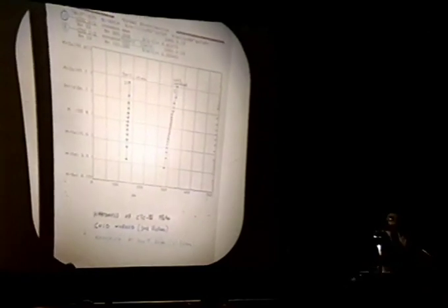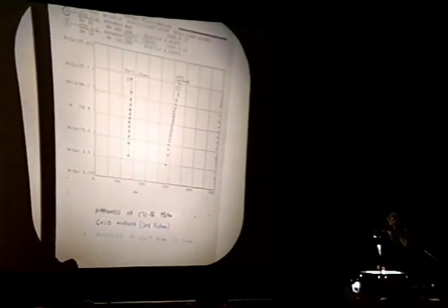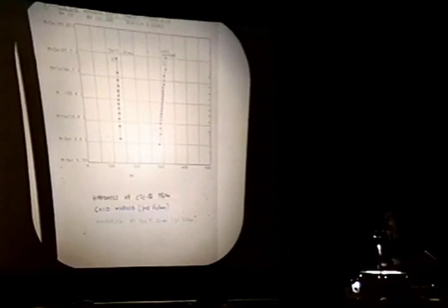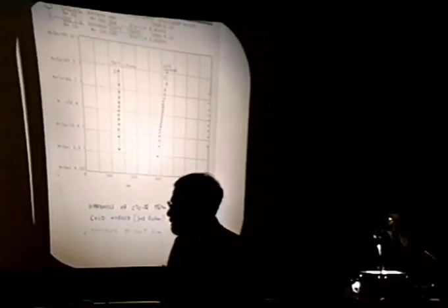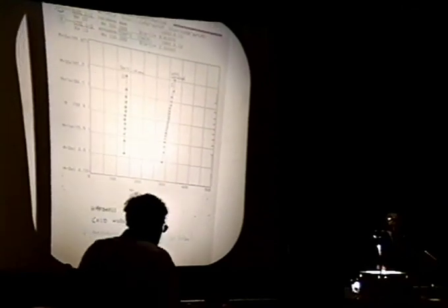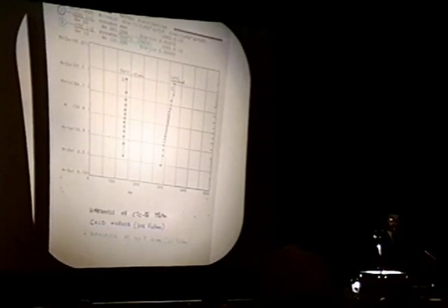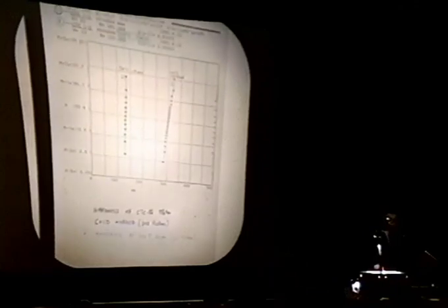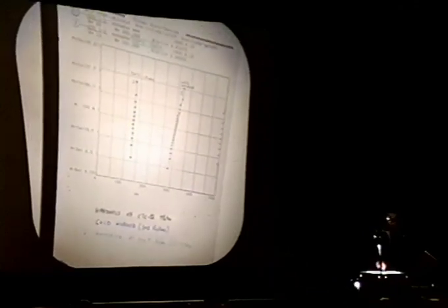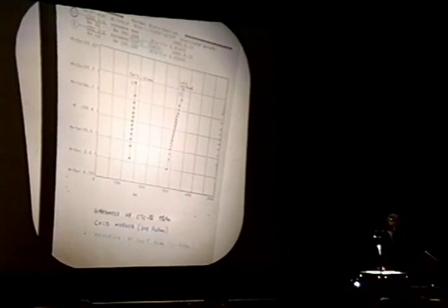This is a similar check we made at 700 Celsius, like the conventional palladium material. And so in this way, the hardness decreased from 300 to about 130, but still a high value, compared with the conventional plate, which is 260.